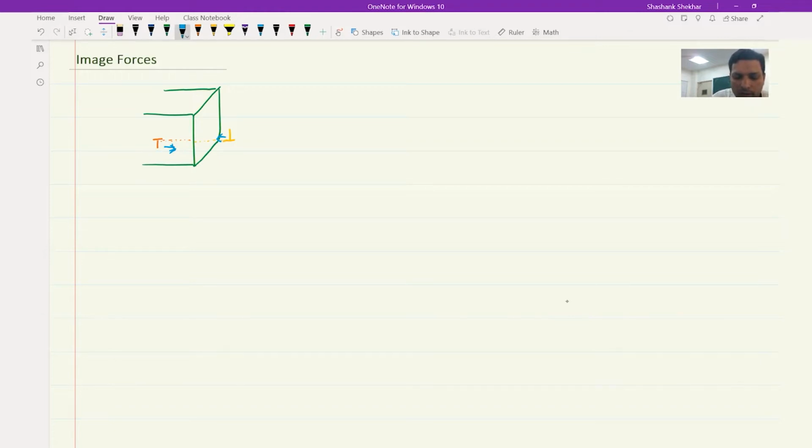So we can calculate the force acting on this dislocation and find out how much force is acting. Let's say this is the distance d. Then the other dislocation must also be placed at a distance d outside the surface. And the interaction between these two dislocations would govern how much force is acting on this dislocation. Let me put it in words what we are doing.